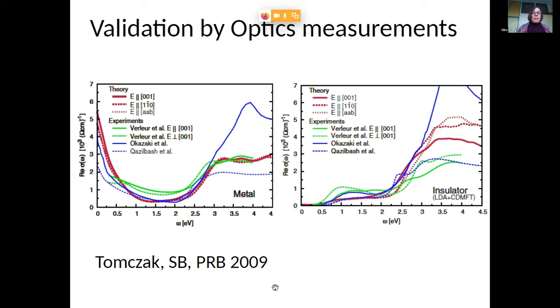Okay, just one short remark on comparison to optics. So this is now optical conductivity calculated from the previous calculation by neglecting vertex correction. So we exclude excitons here. And this is done for the metallic phase on the left-hand side, the insulating phase on the right-hand side. The red curves are theory. And here the different red curves are for different polarizations.